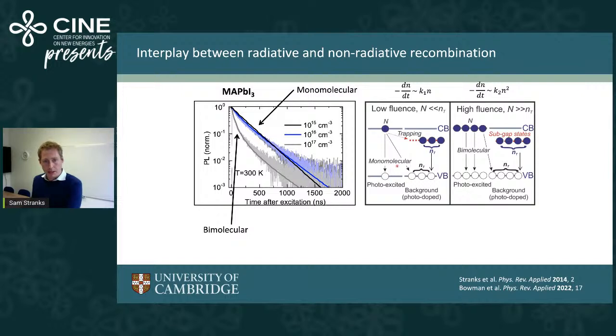And we can explain that by thinking about a trapping model, so where we have carrier traps. And so when we photoexcite, if they're electron traps, we're limited by how many untrapped electrons there are. So this rate of recombination of the electrons and holes becomes quasi-first order. So it really just relies on this density here. So the rate equation is something first order. And so we see a monomolecular recombination kinetic.